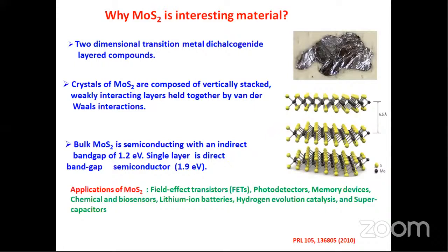Why is MoS2 very important? Basically, the crystal of MoS2 is composed of vertically stacked layers. Two MoS2 layers interact with the weak van der Waals interaction. An important thing, as I told you, is that in bulk MoS2 the band gap is 1.2 eV indirect. But in the monolayer the band gap is nearly 1.9 eV and is direct. Due to that, the material can be used in field effect transistors and photodetectors, as well as for storage, such as lithium ion batteries and supercapacitors.